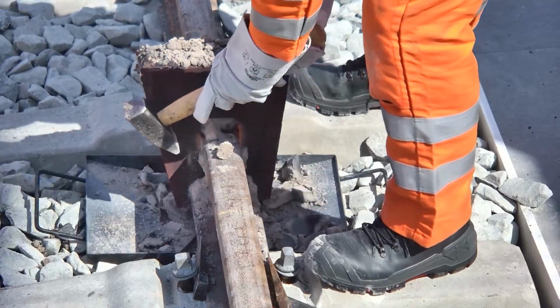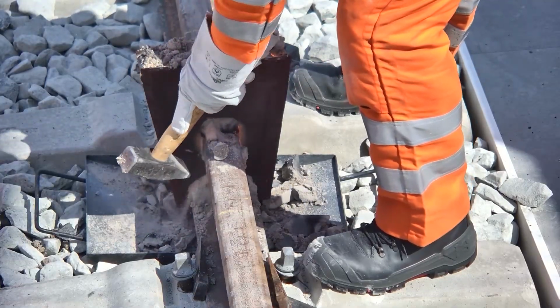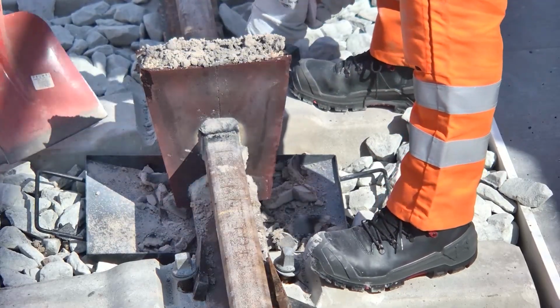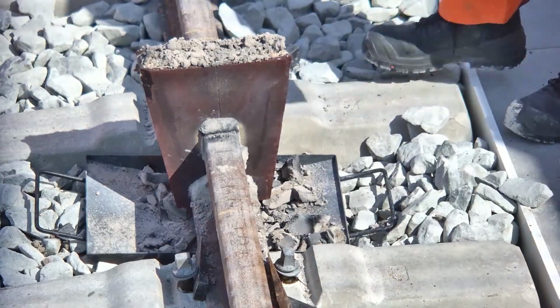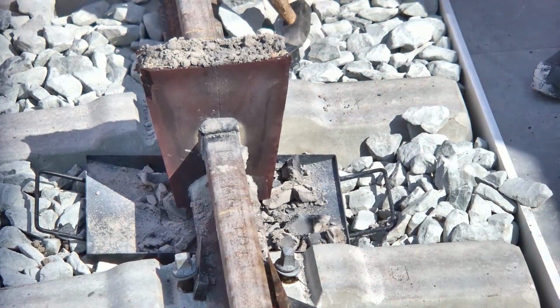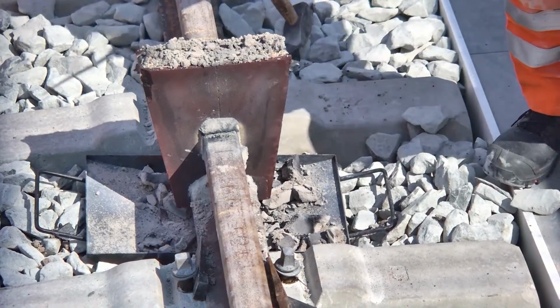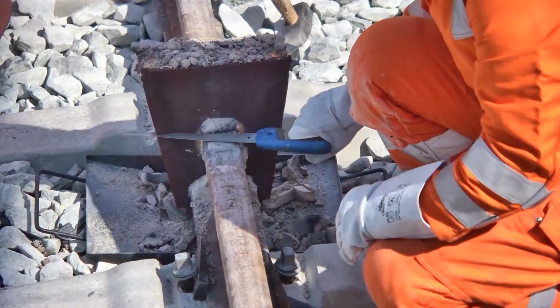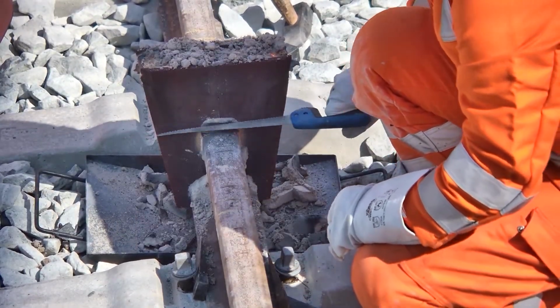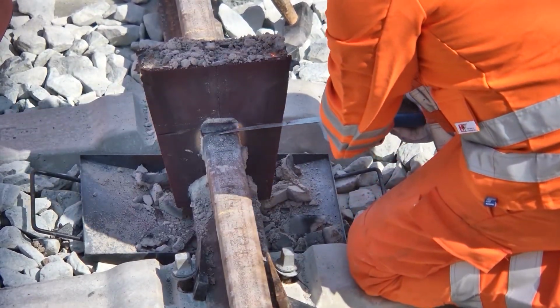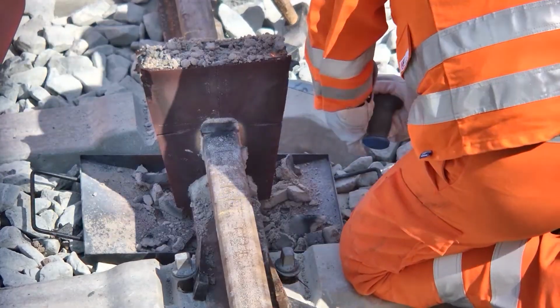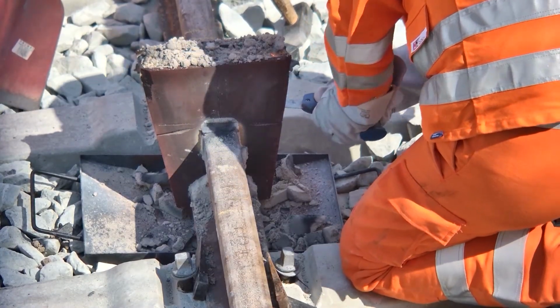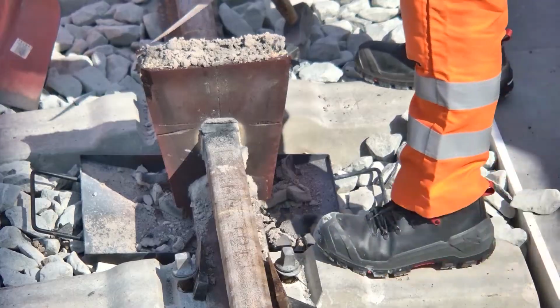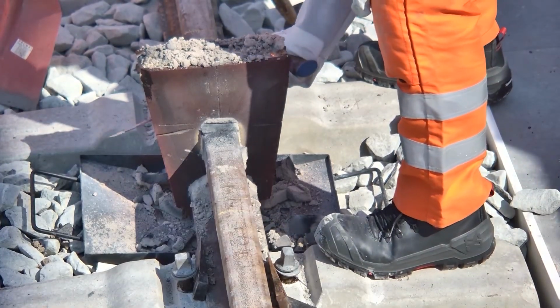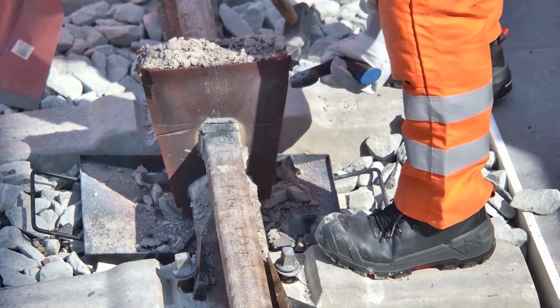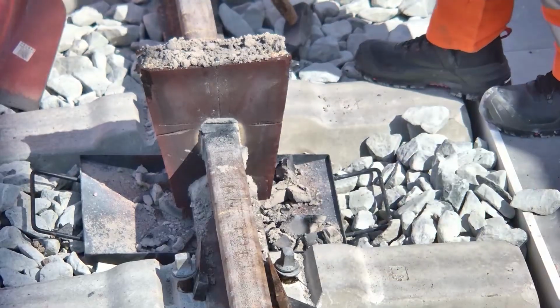Together with the mold. And this is a very crucial operation because obviously while we are shearing it, the steel cools and gets harder and harder and stronger. So it's absolutely important that the weld doesn't get sheared too quickly because that would create cracks, and it also needs to be fast enough so that we don't come into the situation that the steel is already too hard to be sheared.